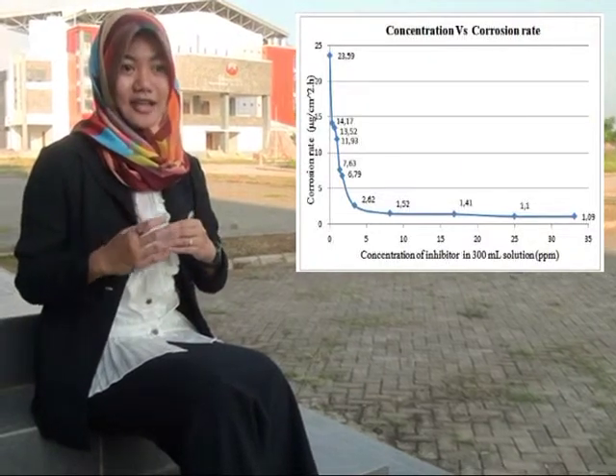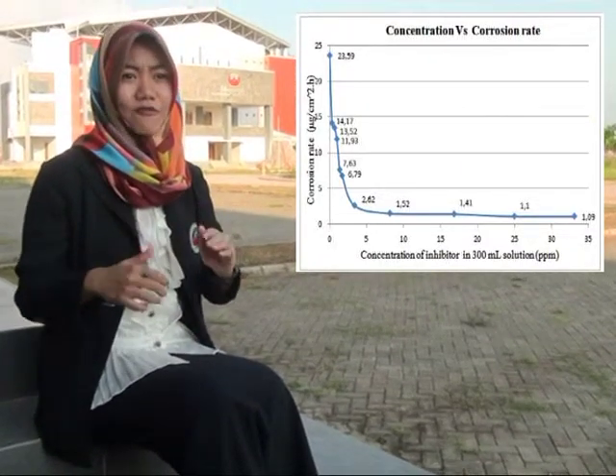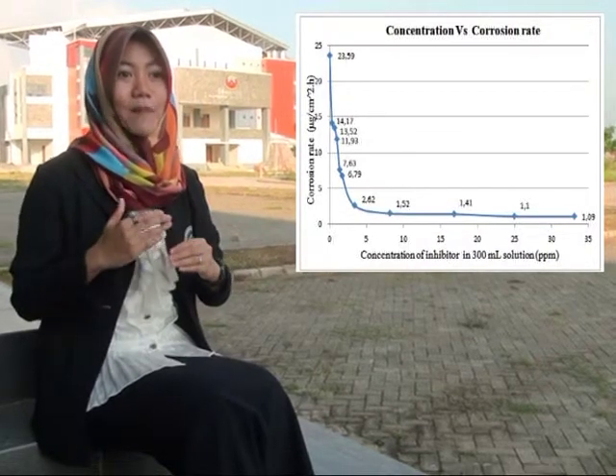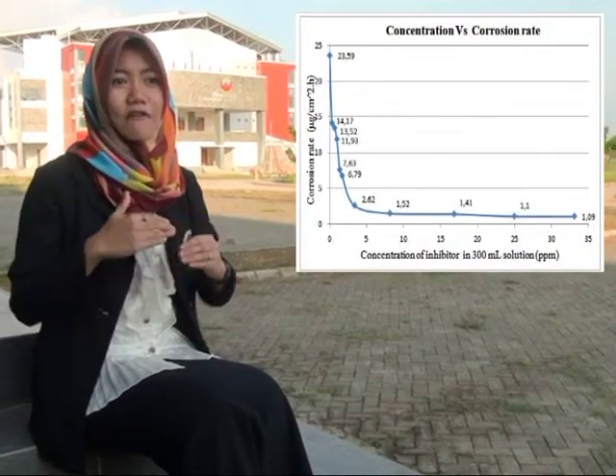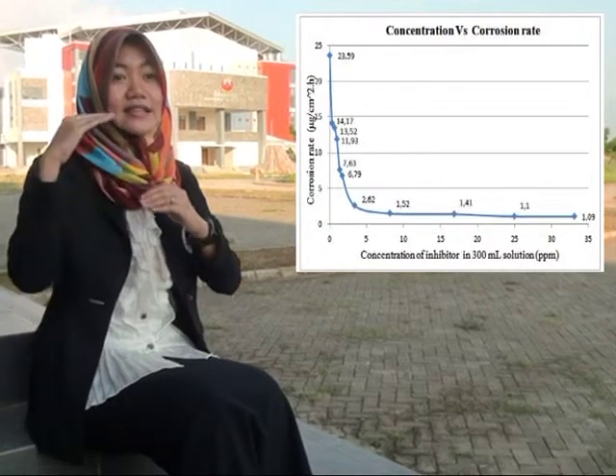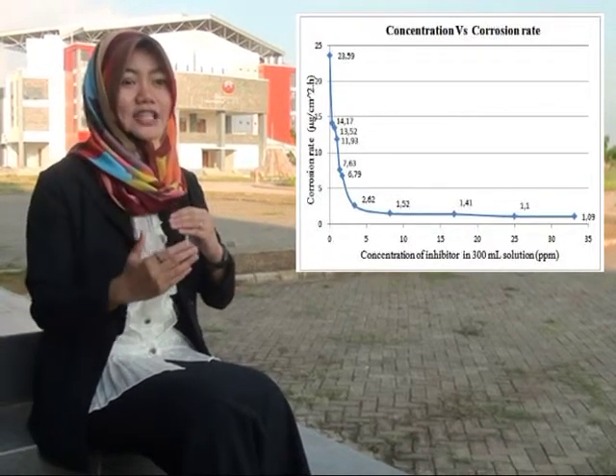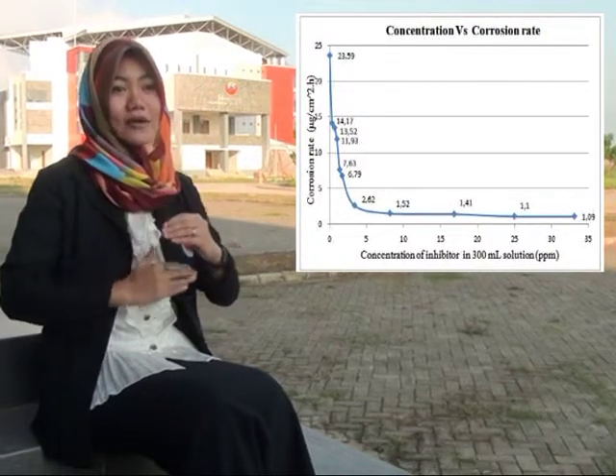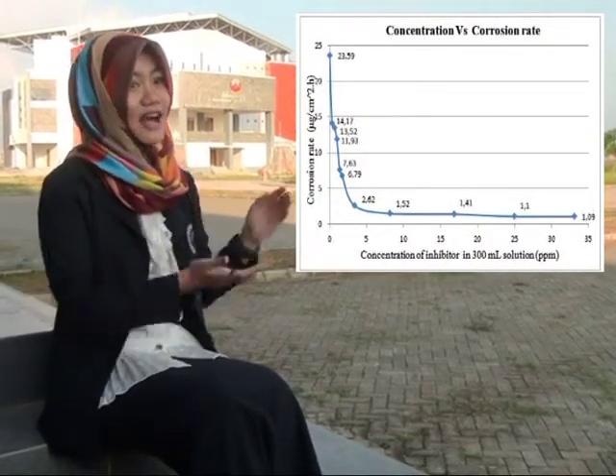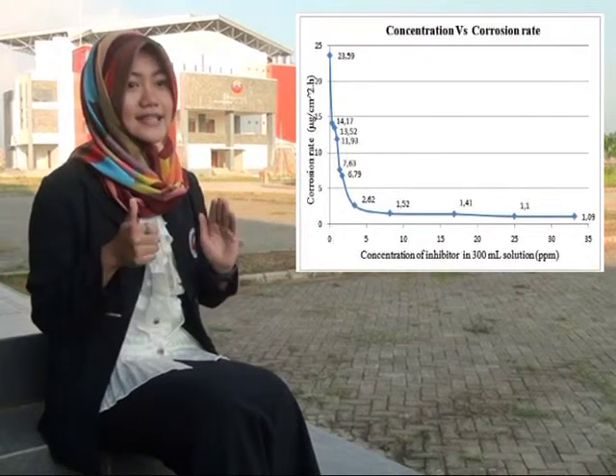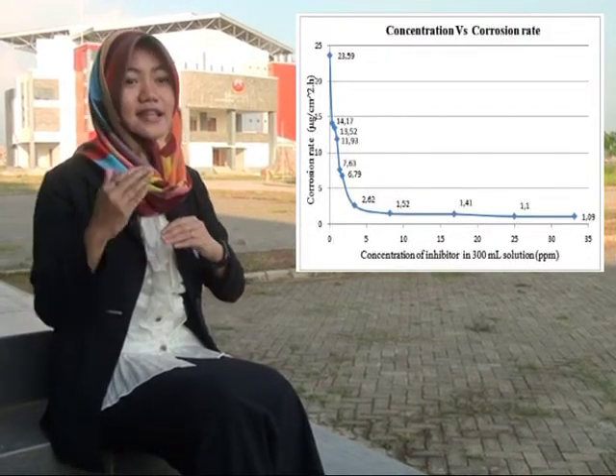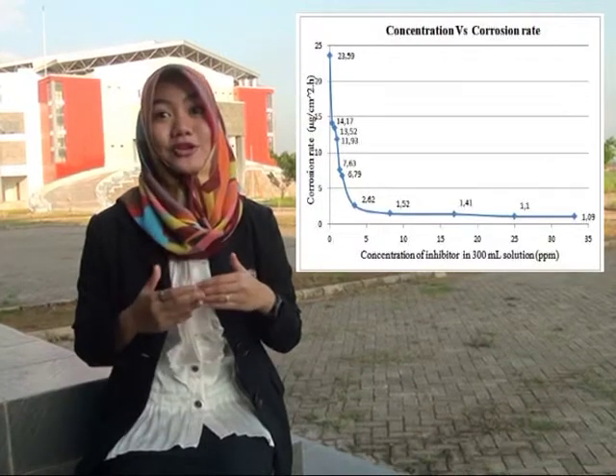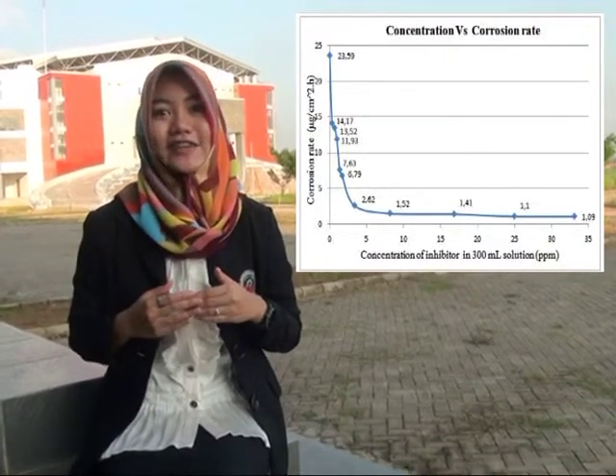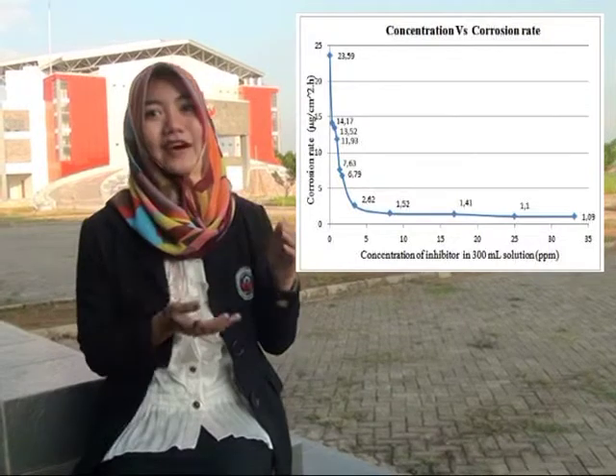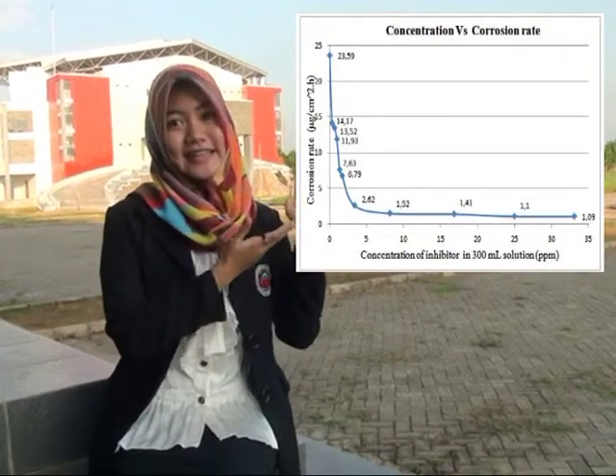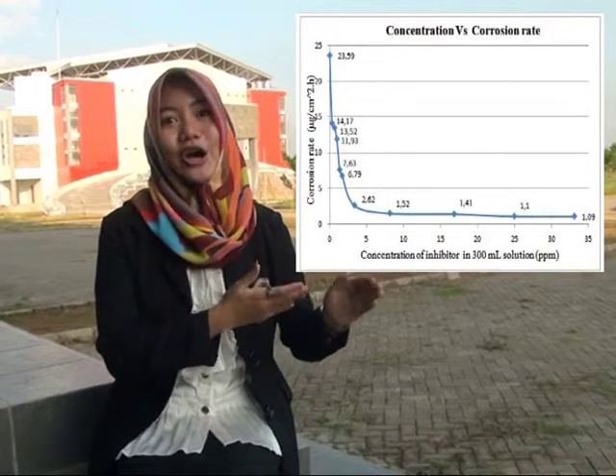In testing the corrosion rate of immersion for 6 days, reflecting the difference between mild steel samples soaked with the addition of inhibitor solution at a high concentration, and soaked with the addition of aloe vera extract solution at a lower concentration, can be seen in the following graph. In immersion for 6 days, it can be seen that at a concentration of 0%, the corrosion rate value is large, and it decreases after the administration of inhibitor with varying concentrations. The graph decreased until at the concentration of